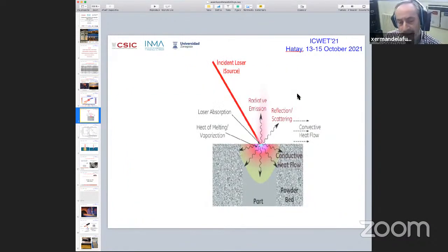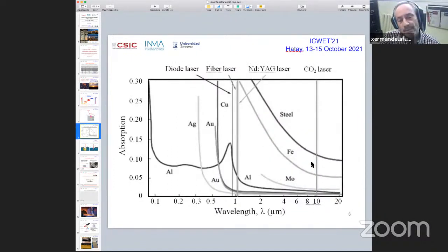Of course, when you irradiate a laser onto a surface, you have incident laser radiation, which can be reflected, scattered, or transmitted, and it can generate absorption to a certain degree, enough to make it heat, to make it melt, and to cause ablation, which we will see later what it is. In any case, what you're usually doing is inputting very localized heat into a material. Not always, but in most cases. And what is important when we talk about metals and alloys is their reflectivity to any specific laser wavelength.